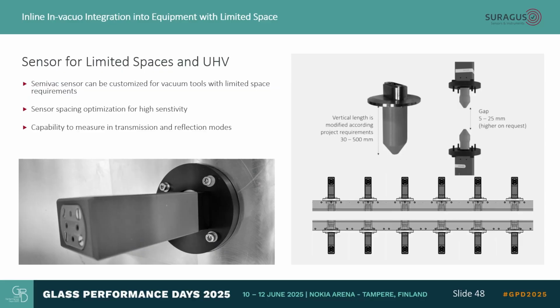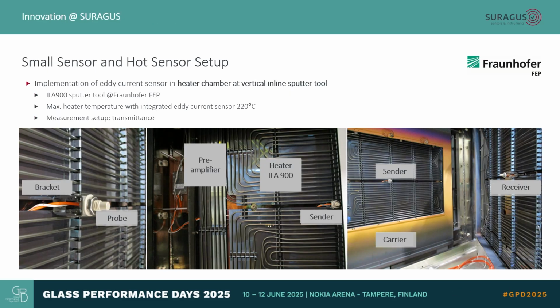But sometimes it's tricky because there are different reasons. Sometimes there's not much space. So we think about how we can have very small sensors or bring the sensors into the machine in a way that they stay mostly outside and don't take much space in the machine. Another way is to have very small sensors that can be fitted in really tight areas, but at the same time are able to withstand heat. So we have sensors that can withstand quite some heat, and now we are trying to push the limits up to 500 degrees. At the moment, we are just able to do it up to 220 degrees.